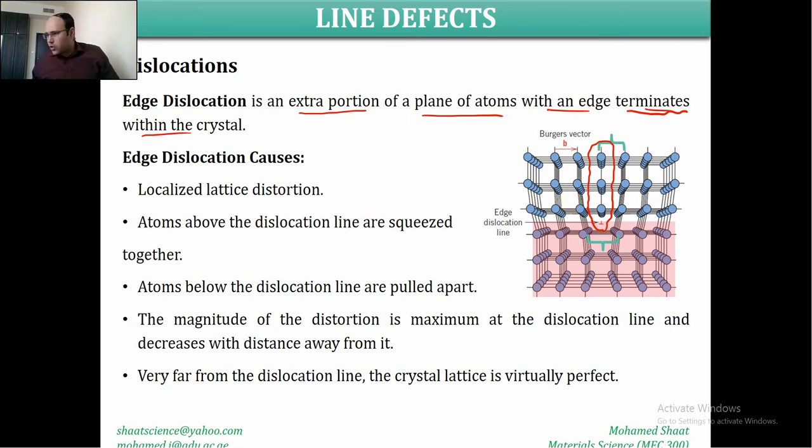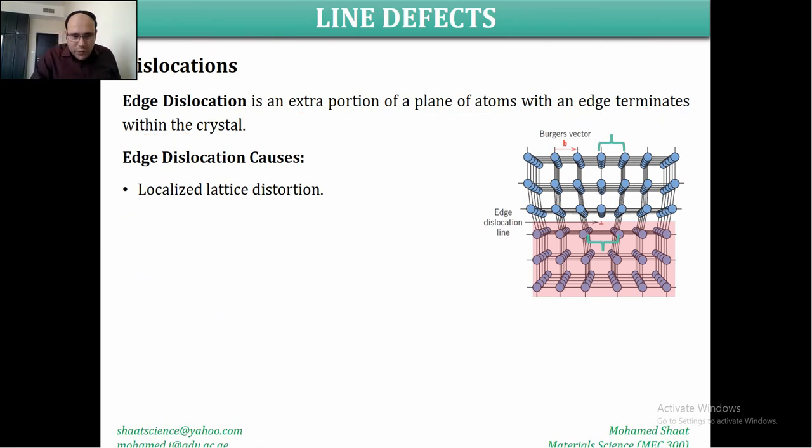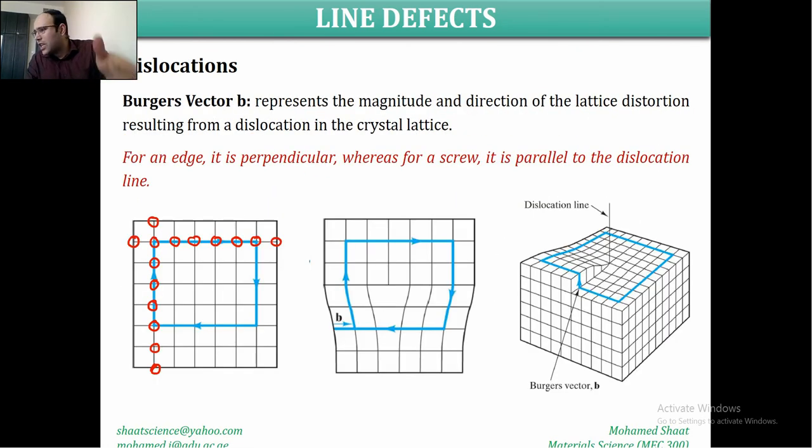What is the problem of this edge dislocation and why are we considering it a defect? Because it does change the regular structure of the crystal represented here. This is the ideal crystal structure, but because of squeezing in another plane as shown here, do you see this plane? This is an edge dislocation. This is the first plane, and there is a plane here, another plane, and for some reason we are inserting an excess or extra plane, half of a plane, not a complete plane, and it terminates here. So this is the end of this plane that is squeezed between the other planes.